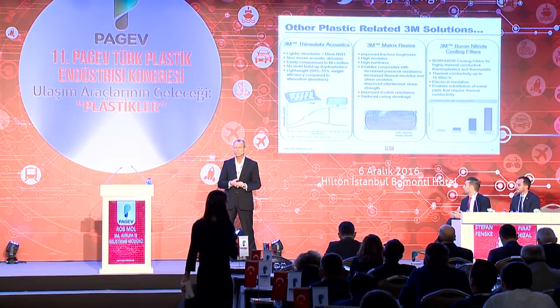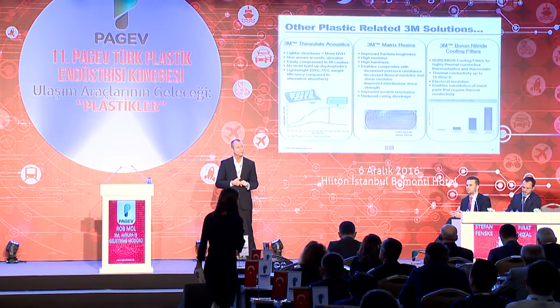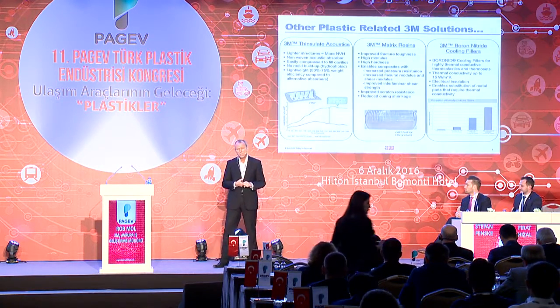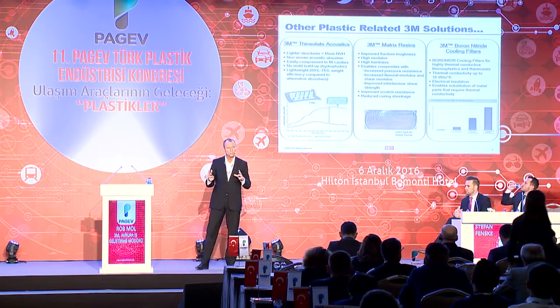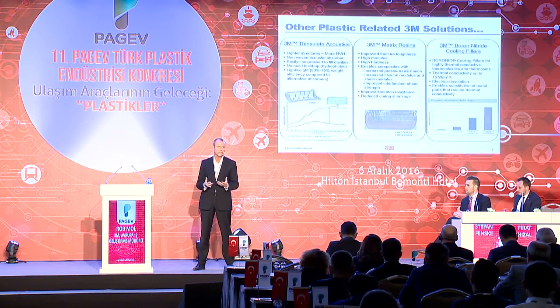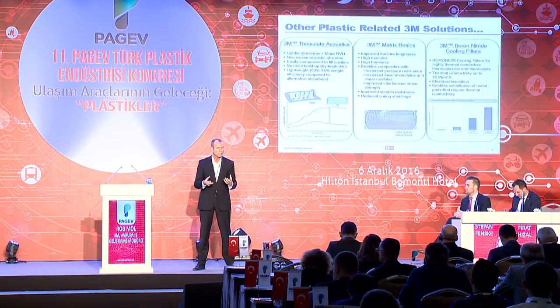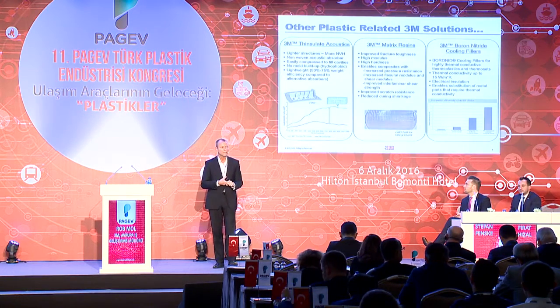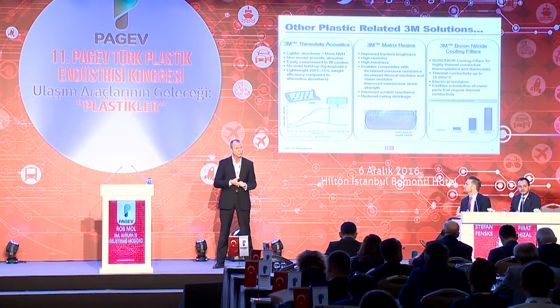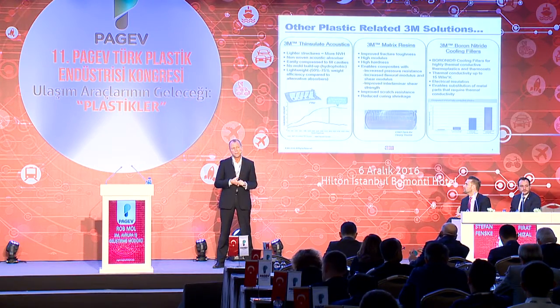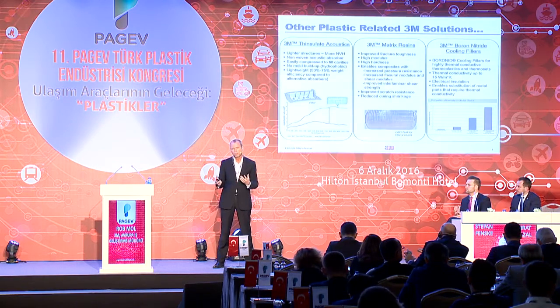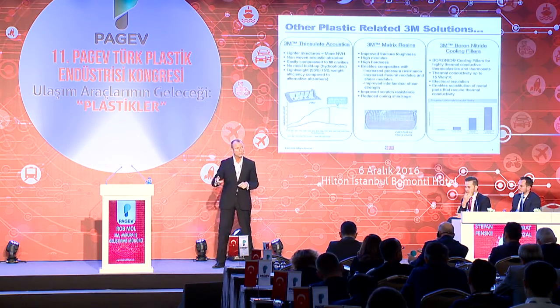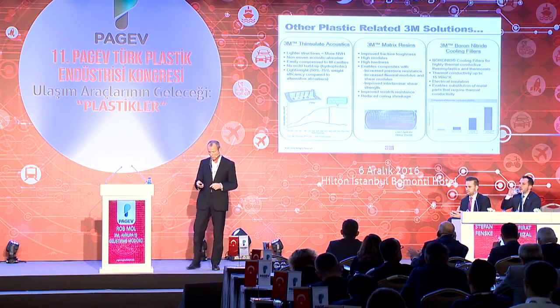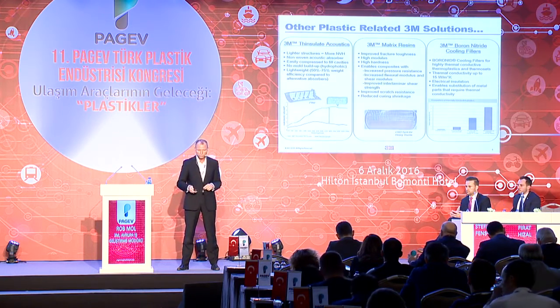And on the right-hand side, we're talking about cooling fillers, boron nitride cooling fillers. Why is that lightweight? If you use cooling fillers like this in a plastic material, in a polymer, you will make it more thermally conductive, and it can also work as an electrical insulator. That means that you can replace metal parts. For instance, in an engine where you need these features, you can replace it with a polymer. So again, that's a lightweight solution as well.